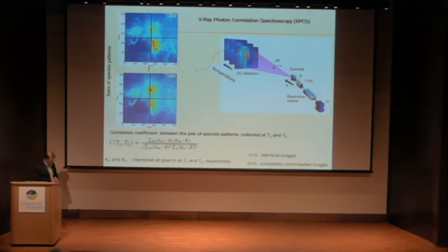And we apply the usual approach. We analyzed the speckle patterns at different temperatures and calculate the correlation coefficient between these patterns, so that where the patterns are exactly the same, the correlation coefficient equals 1, and in a completely uncorrelated state, it is 0.